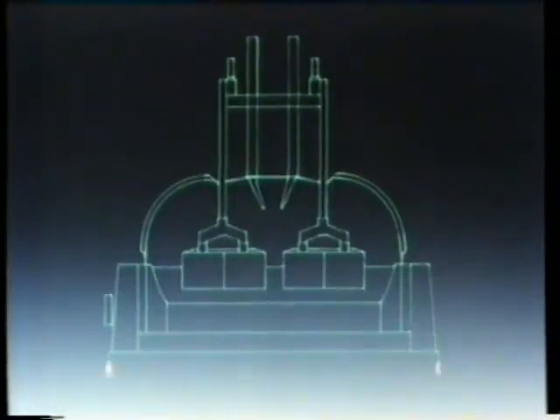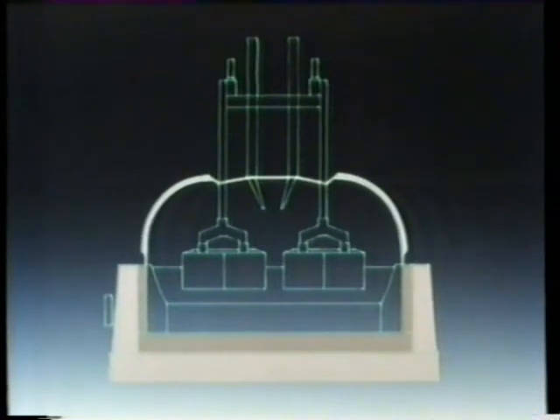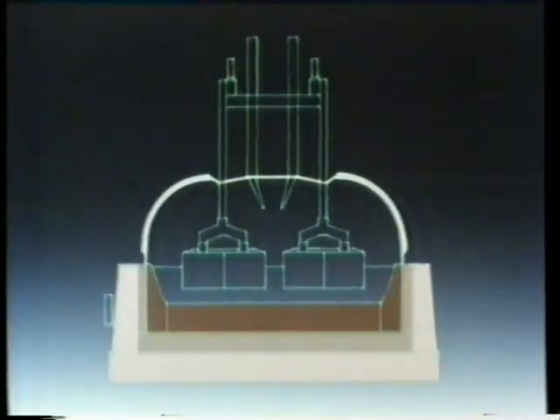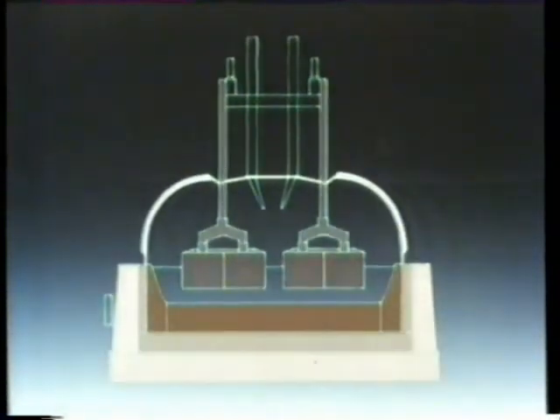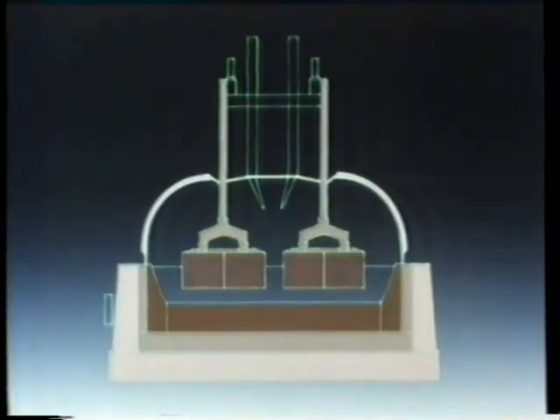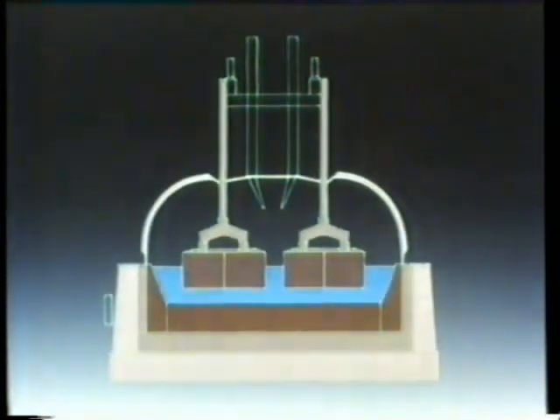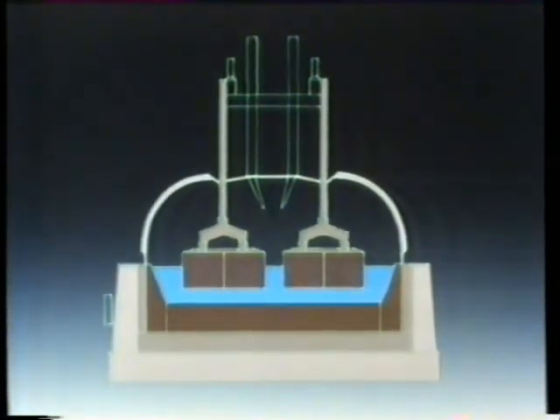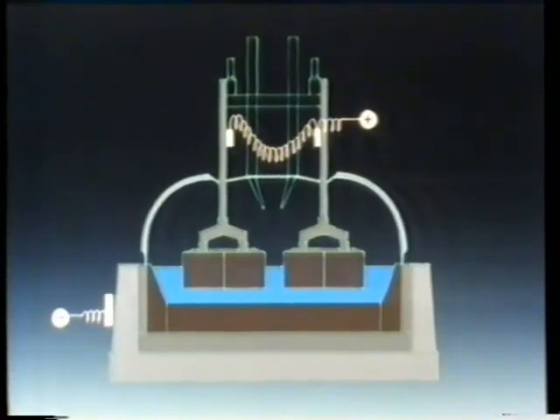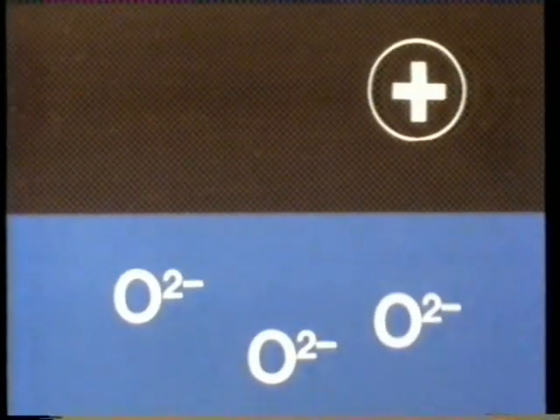This is the end view. There's a steel shell lined with carbon blocks. Blocks of pure carbon mounted on metal rods dip down into it, and it's filled with cryolite, another aluminium compound in which the alumina is dissolved at 970 degrees C. The cell and lining blocks are made the cathode, negative, the carbon blocks the positive anodes. At the anodes, oxide ions give up electrons and become oxygen gas.